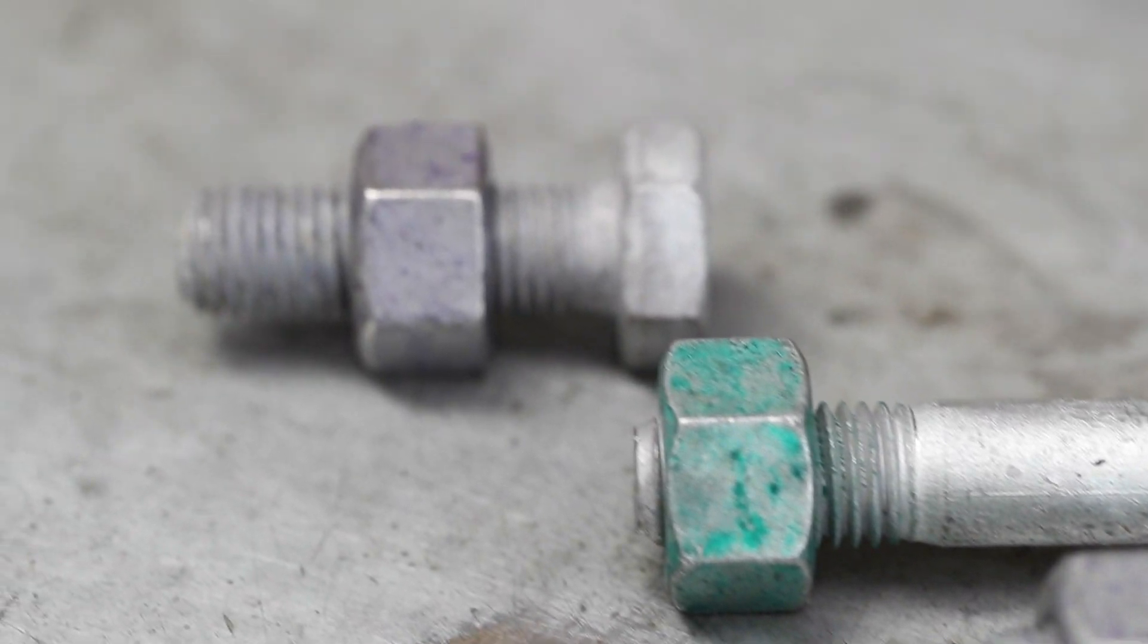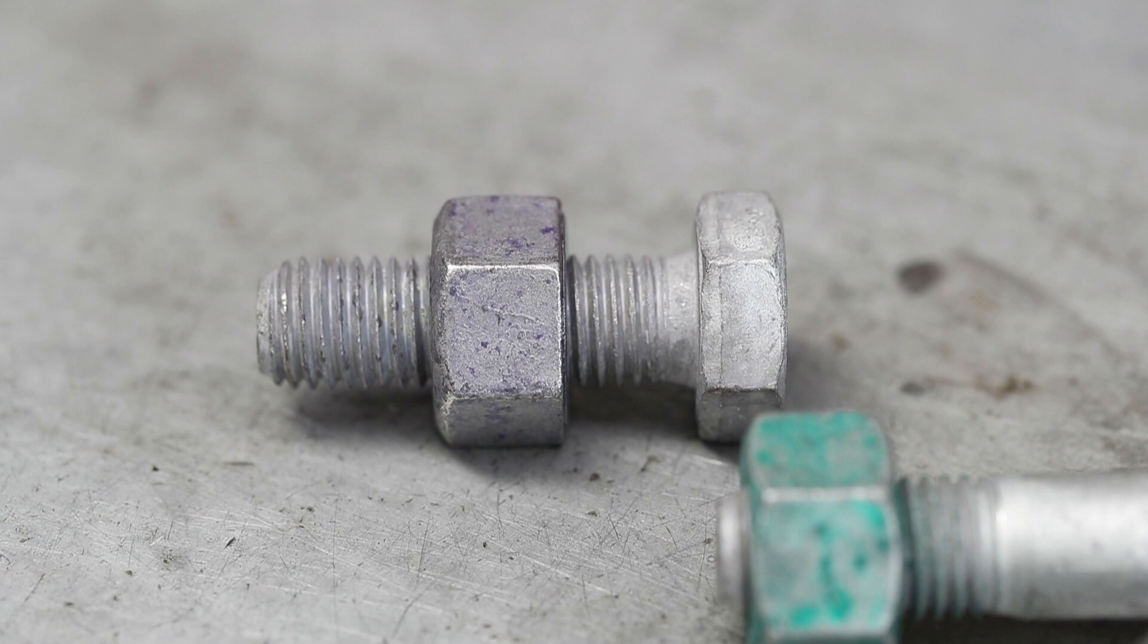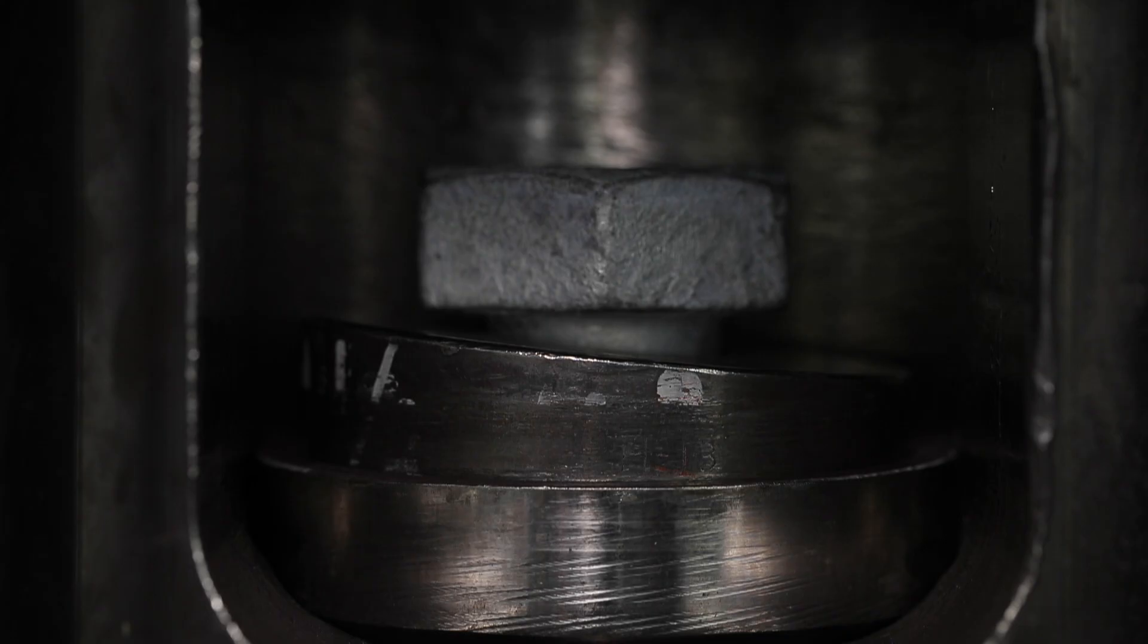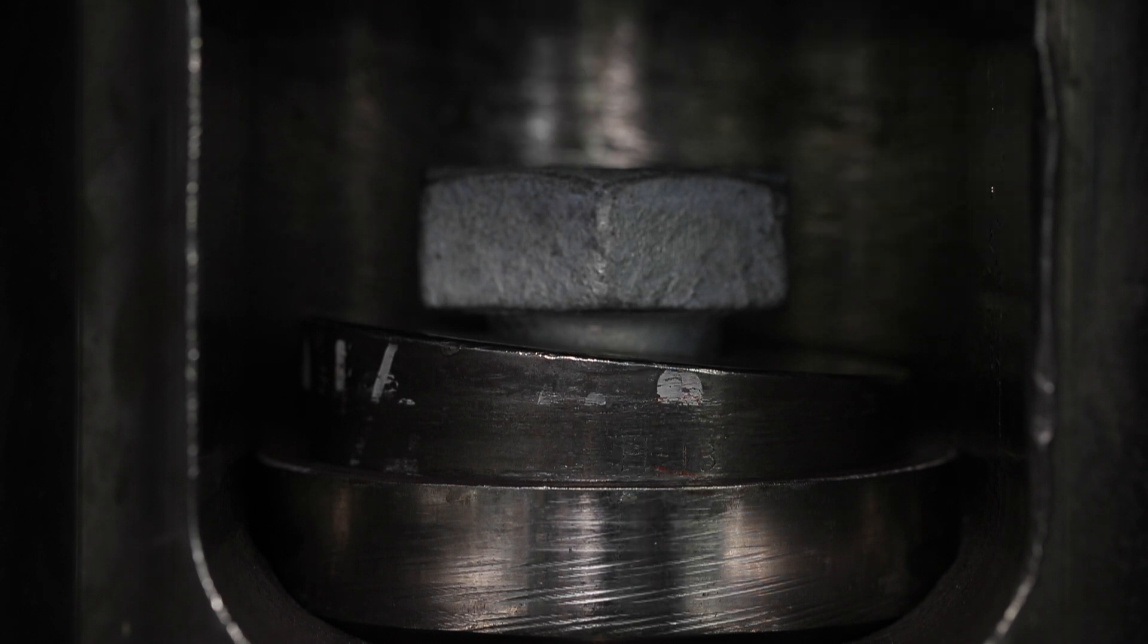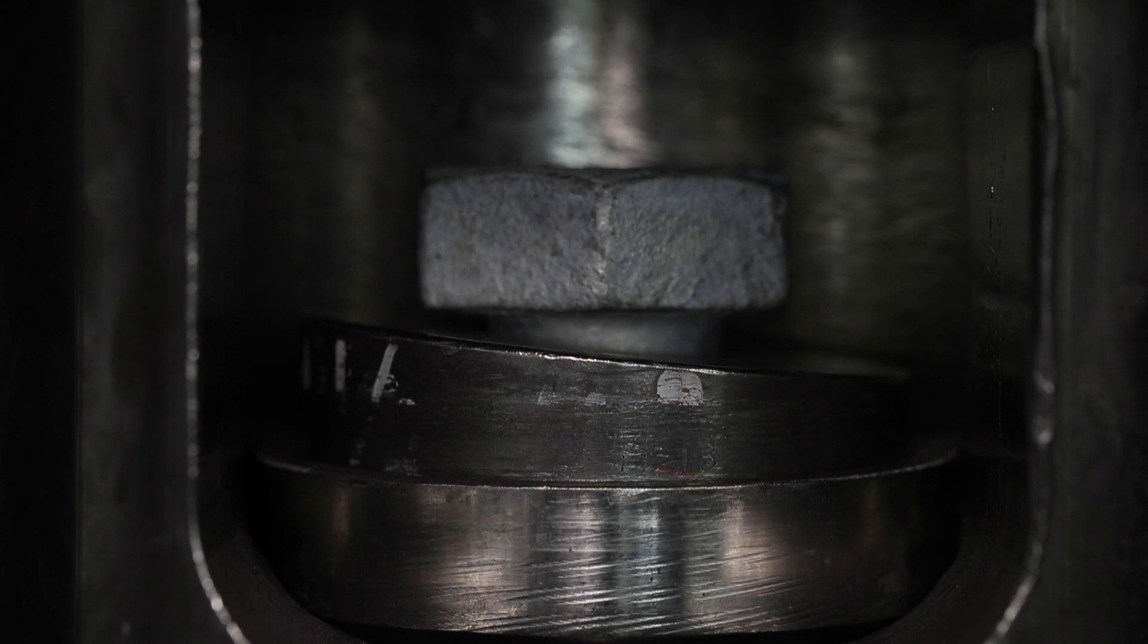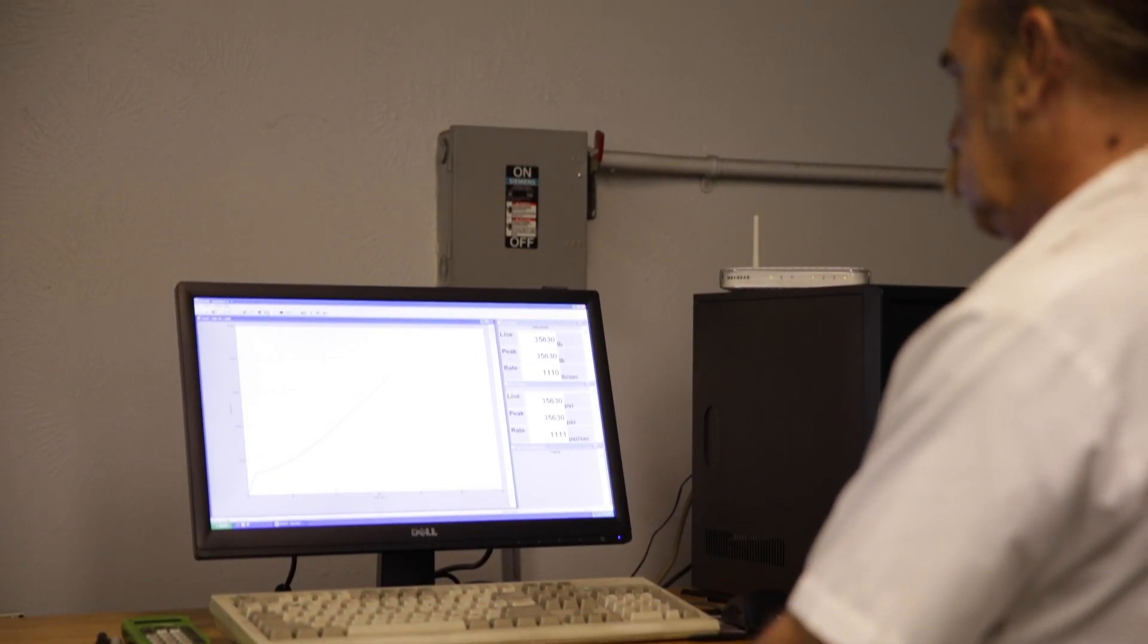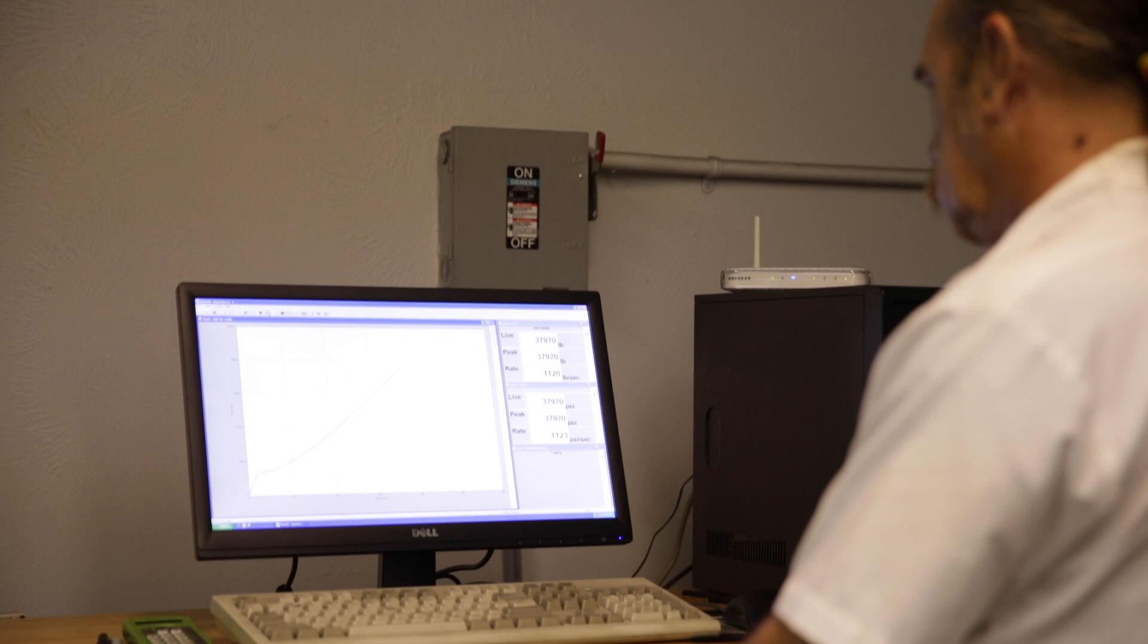A 10-degree wedge angle is the most commonly used. If a wedge angle greater than required is used, the test may result in a lower tensile value. Generally, the greater the test angle, the lower the tensile performance of a given bolt will be.